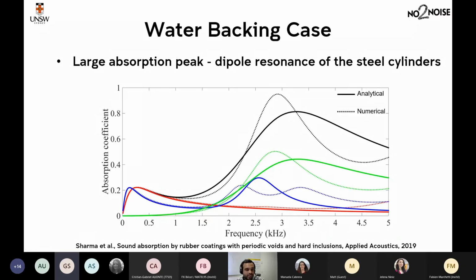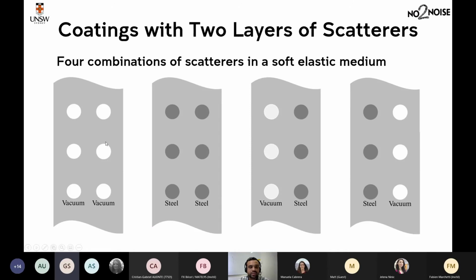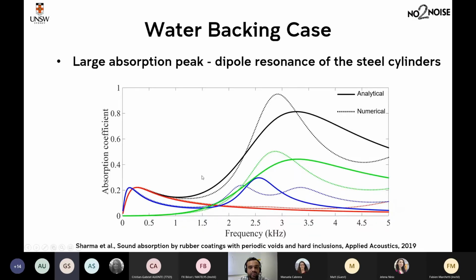And this is with water backing, when you have water backing on both sides. So remember, when you have water backing, you don't really have very strong mass spring resonance because you don't have the mass of the backing, right? So you only have one major peak, this peak, and this peak is due to dipole resonance of your hard inclusions. So you see that when you have two layers of voids, you don't really have dipole resonance. This is not due to dipole resonance. This is due to interference between the waves by these two scatterers. When you have two hard inclusions, you have some dipole resonance.